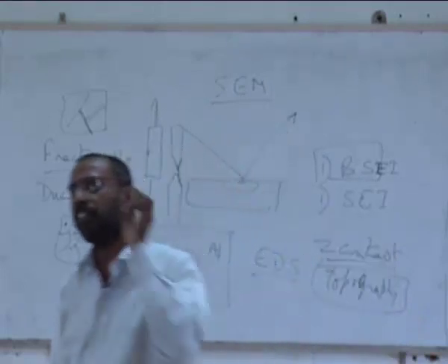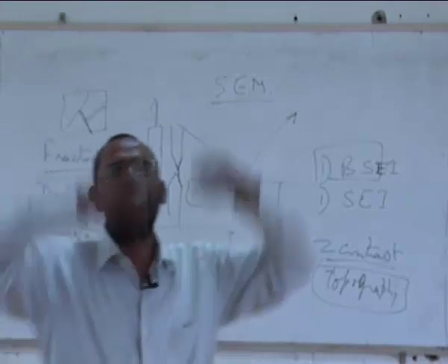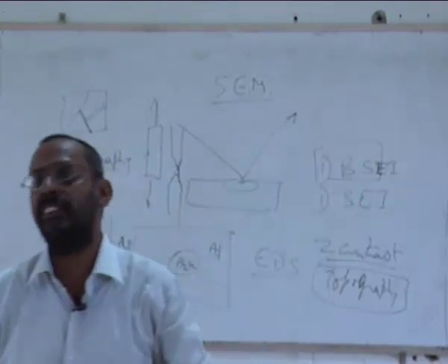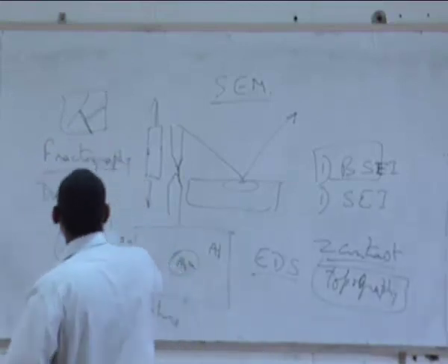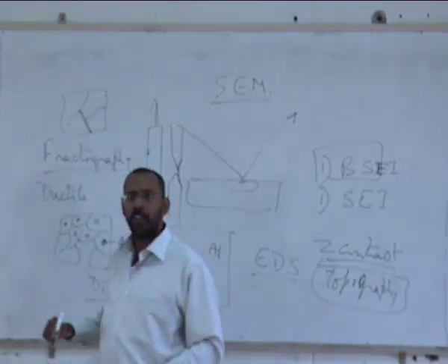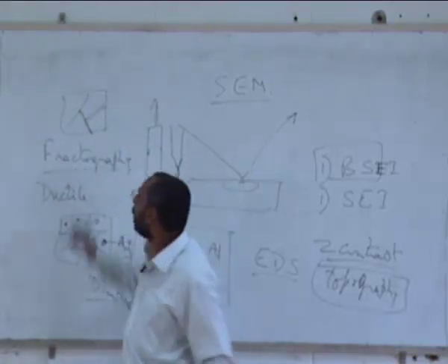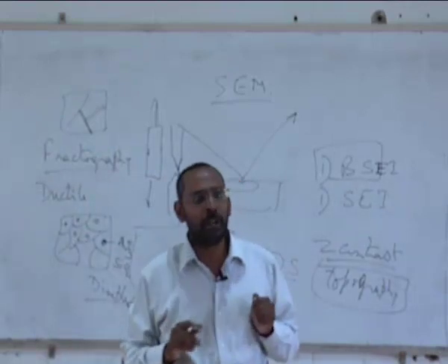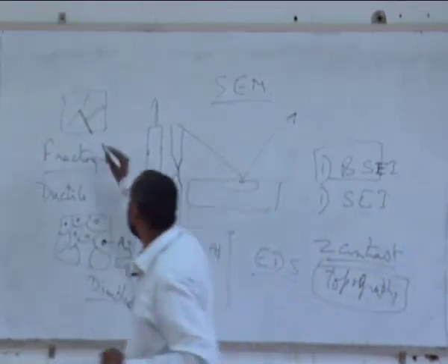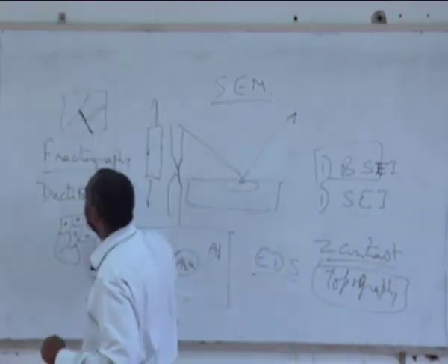We know that if you want a stainless property, the chromium content has to be maintained at a minimum of 12%. Only when the chromium content in any region is higher than 12% do we call it stainless steel. Otherwise, we don't. The moment carbon takes away chromium, the chromium content near the grain boundary falls below 12%. Immediately, if there is an acid medium or some corrosive medium around this sample, the grain boundaries get attacked.